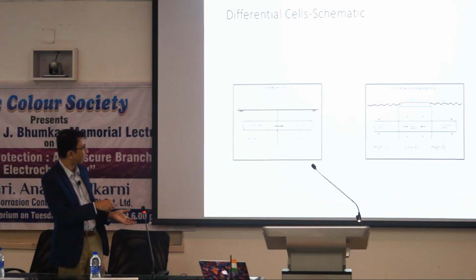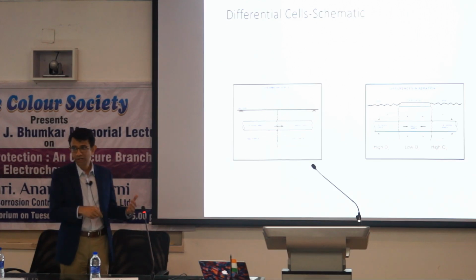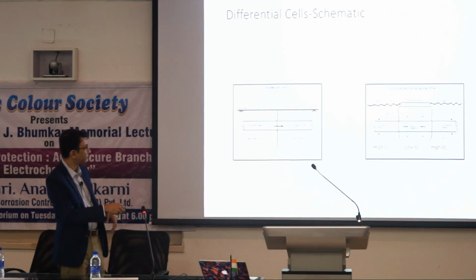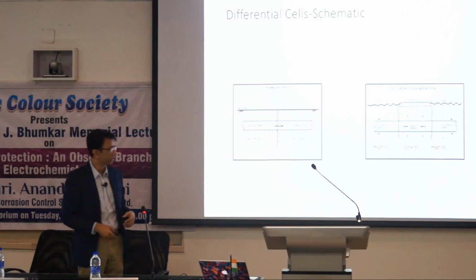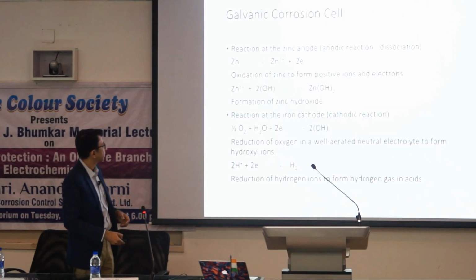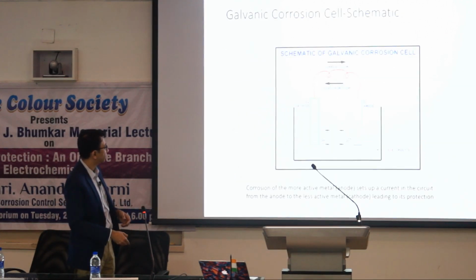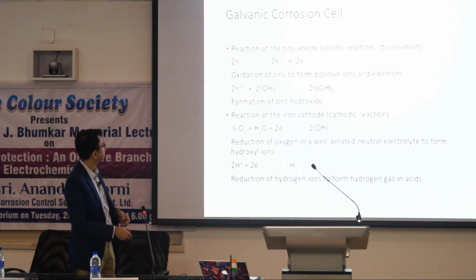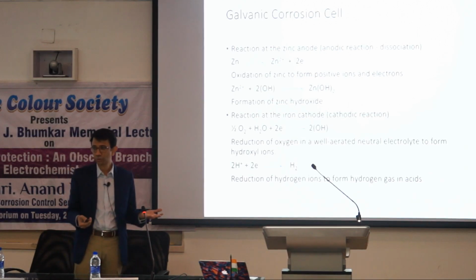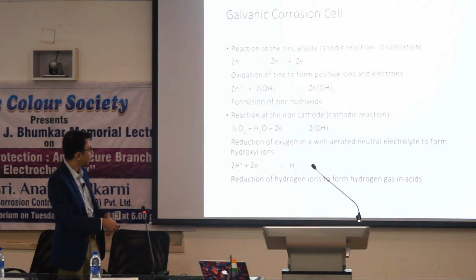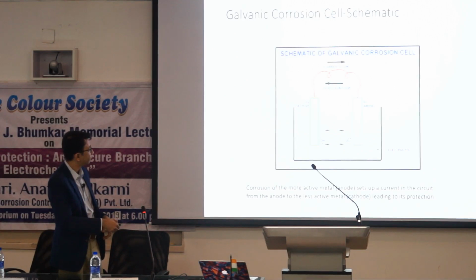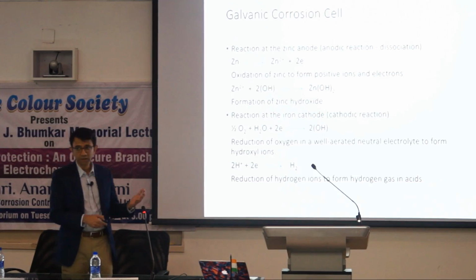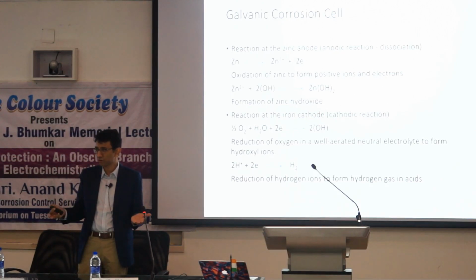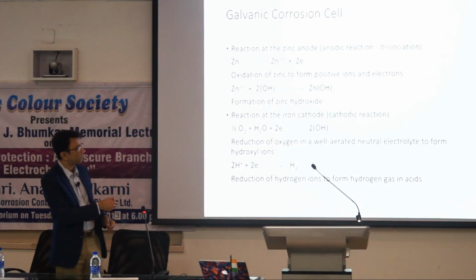As a result of which we have one area which is relatively cathodic to the other, one area which is anodic. The anode obviously corrodes. As you can see here, one more issue that I would like to emphasize is that this oxidation reaction is basically what is corrosion. And at the cathode, at the iron sheet, we find that there is no corrosion because whatever electrons are needed for reduction of oxygen, which is a natural phenomenon, are supplied by zinc.